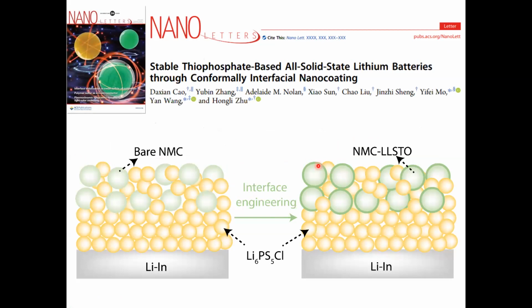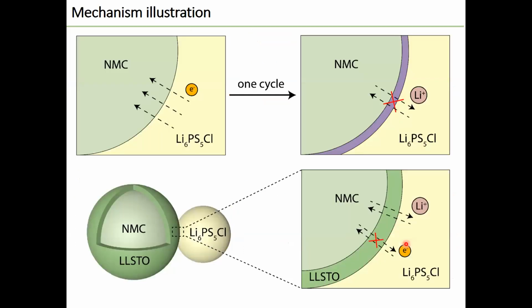The coating material is shortened as LLSTO, and the sulfide electrolyte is lithium phosphorus sulfide chloride. To avoid the side reaction between sulfide electrolyte and lithium metal, we use lithium indium as anode. The fundamental mechanism for interface stabilization is illustrated in this schematic.